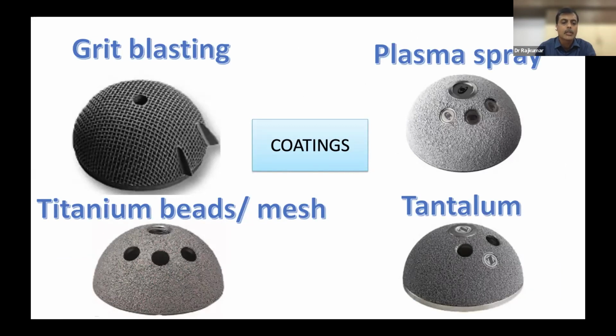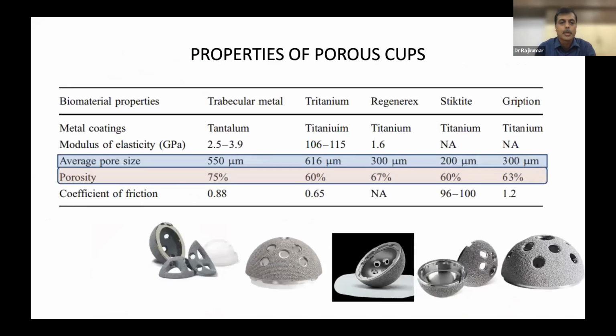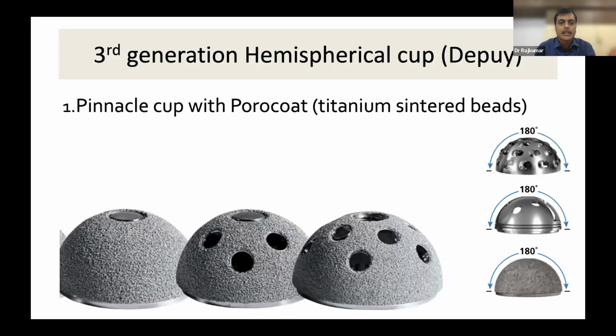The most common coating we use is the titanium beads, where the titanium beads increase the porosity, but more porosity is provided by the tantalum cups and the Gription coatings. So the coating is also important. The most highly porous cups are the trabecular metal cups and the Gription cups, which help in revision scenarios and in osteoporotic situations.